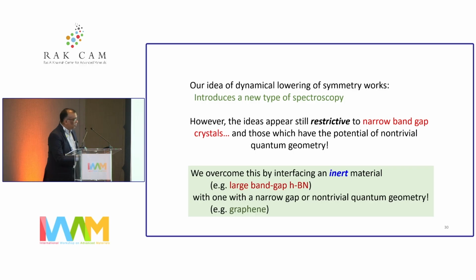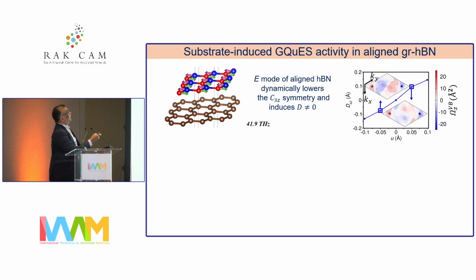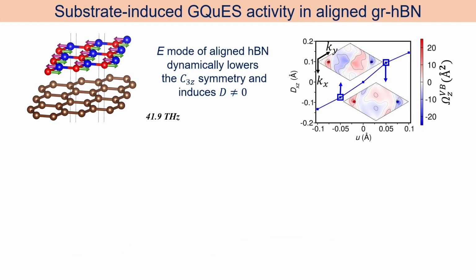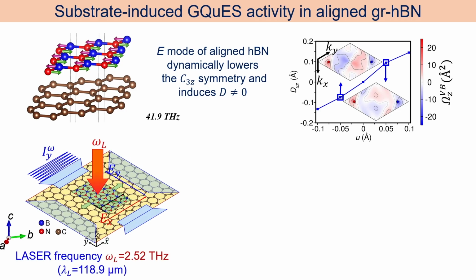So if you interface boron nitride on graphene, you will see that the vibrational mode of boron nitride also induces oscillations in the electronic structure of graphene and also gives rise to a Berry curvature dipole, which is linearly proportional to the vibrations of hexagonal boron nitride. So this is our proposed experimental measurement. You have hexagonal boron nitride, which will have a macroscopic oscillation or the optical mode oscillation, and which is deposited on graphene, and you measure Hall emission from that.